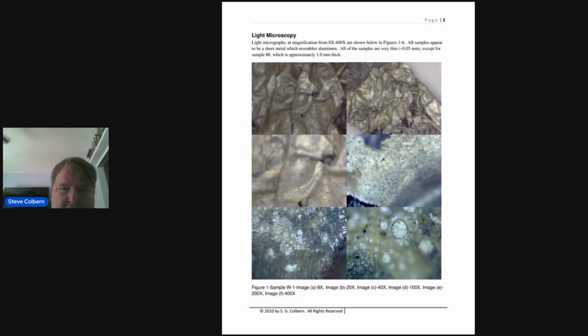Here are some of the pictures, light micrographs of sample W1. You can see the crumpled appearance, and the surface was very interesting. Some of these samples seem like they might have some sort of a coating on them. I wasn't sure if it was an actual coating, or if it was soil adhering to the material. It seemed like a coating to me on at least a couple of them, and I thought those circular or oval shapes on the surface were very interesting. They could have been microstructures of some kind. It seems to appear very differently from aluminum of human manufacture.